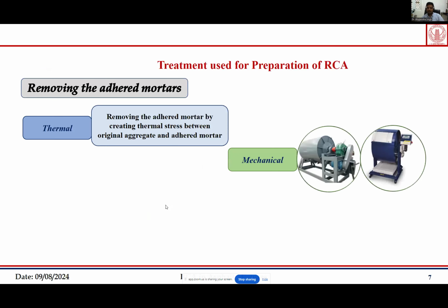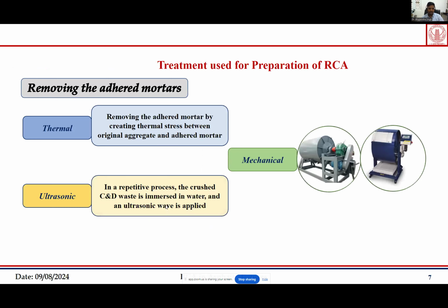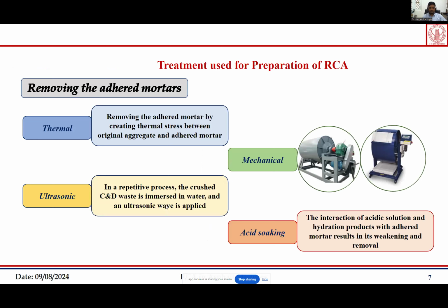Now there are many methods of the treatment of that RCA. So first type of methods comes under the category of removing the adhered mortar. We want to remove whatever mortar is present on the aggregate surface. So first treatment type is thermal. We remove the adhered mortar by heating it up to a very high temperature. Due to that heat treatment, because the coefficient of thermal expansion of aggregates and the coefficient of thermal expansion of adhered mortar are different from each other, some thermal stresses develop, and then the adhered mortar gets detached from the surface of the aggregate.